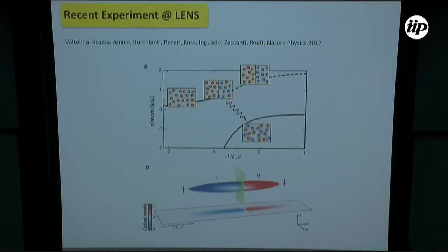So an experiment to confirm whether this transition is supposed to take place was performed very recently in Florence at LENS. And they used what is called the upper branch of a Feshbach resonance to create a strongly repulsive three-dimensional Fermi gas. Now, in the experiment, the system is unstable against molecule formation. So to circumvent the problems due to molecule formation, what they did is to create an artificially already ferromagnetic phase, a phase where the spin-up and the spin-down particles have separated, and they have studied the stability of these two separated clouds.